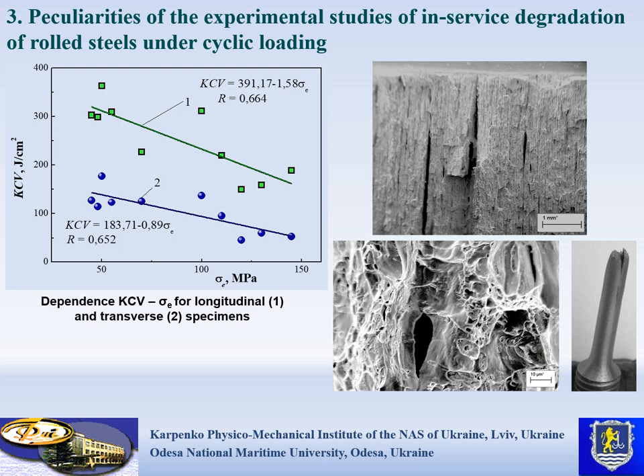The revealed essential difference in impact strength of longitudinal and transverse specimens is caused by development during service of delamination in the rolling direction. It was confirmed by macro and micro fractography of specimens.